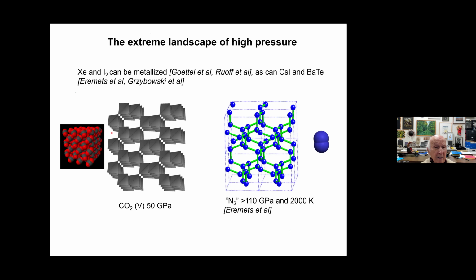There is a variety of structures, and we'll see the reasons for that. One of the interesting things that happens is that if your students ask you why is CO2 so different from SiO2, one thing you can tell them is if you apply pressure, CO2 becomes like SiO2. That is, under high pressure, only 50 gigapascals, that's 500,000 atmospheres, CO2 goes into a quartz-like structure. And nitrogen, diatomic nitrogen gas, a very strong triple bond in a molecule, goes into a 3-coordinate framework, which is similar but not identical to the frameworks of phosphorus and arsenic at about 1 million atmospheres.